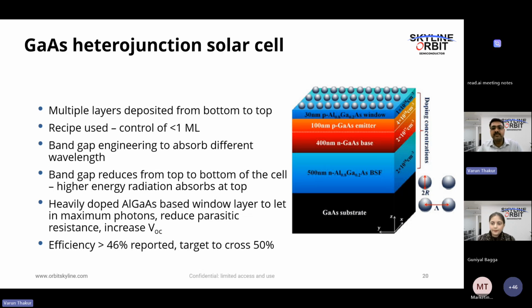So here, one of the most important elements, a fabrication, a deposition element, is the window layer. I'll explain more about it later. This AlGaAs-based window layer lets in the maximum number of photons and reduces the parasitic resistance. In this kind of solar cell, the maximum reported efficiency is more than 46%, and the target is to cross 50%. Keep in mind that this efficiency is not a single sun efficiency. When we see efficiencies reported like 20-25%, those are all single sun efficiencies. But in lab tests, we want to know the maximum capacity of the solar cell, so we shine light equivalent to multiple suns. It could be two or three suns also, right?